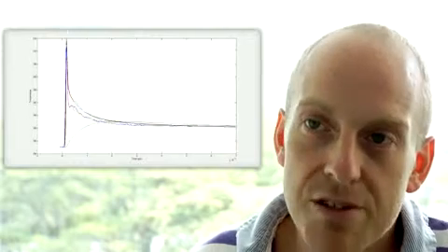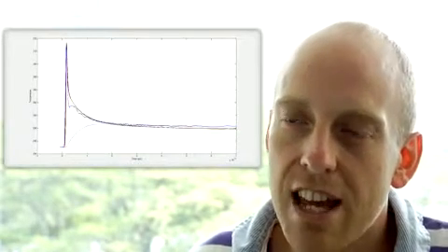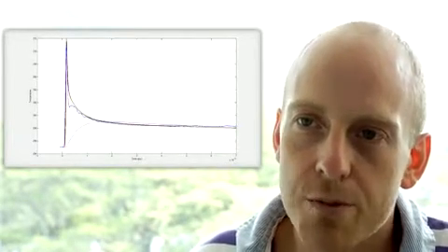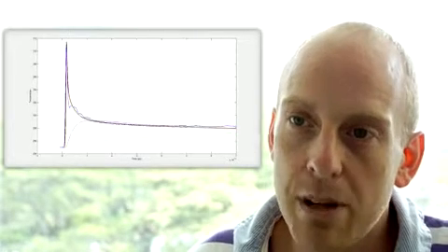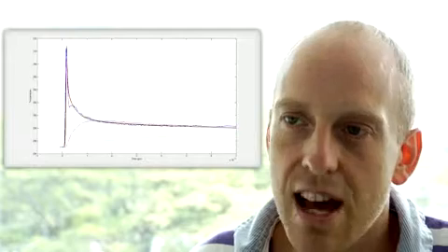The two hot bosonic modes themselves may further cool by transferring energy to cold phonons and cold spin fluctuations. We find that with this model, the doping-dependent relaxation line shapes are very well reproduced at all dopings.